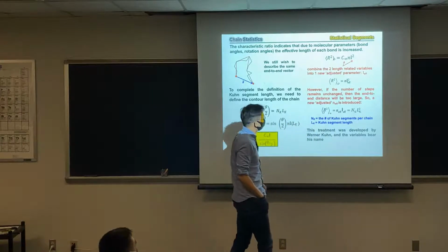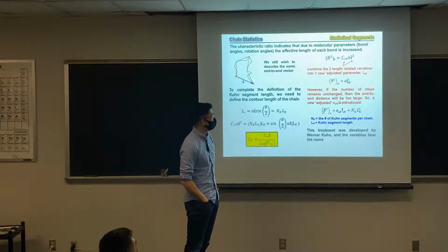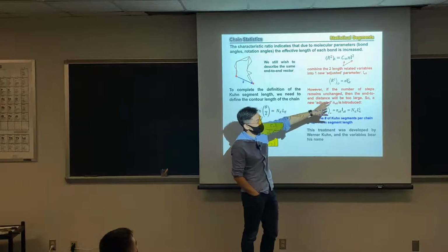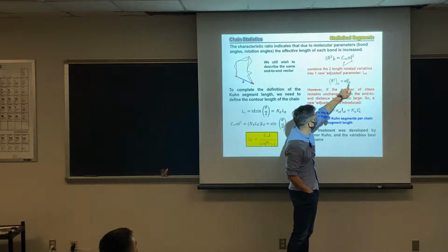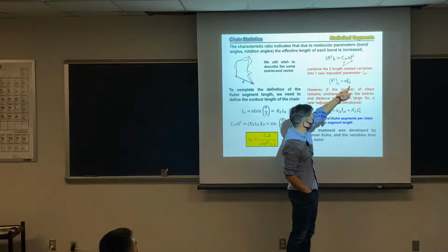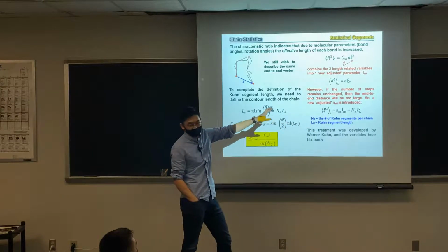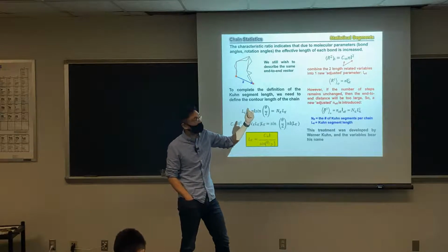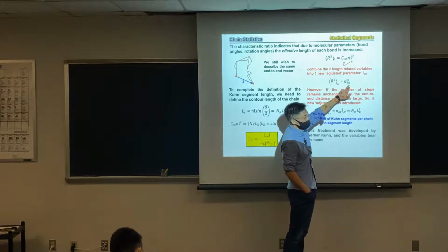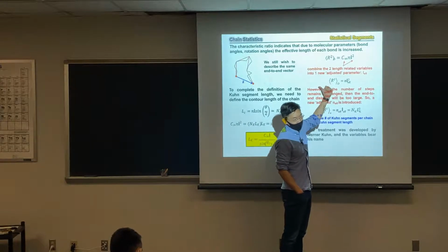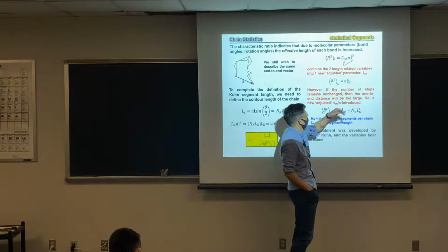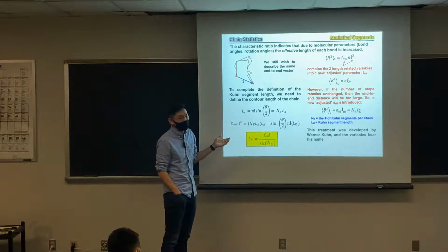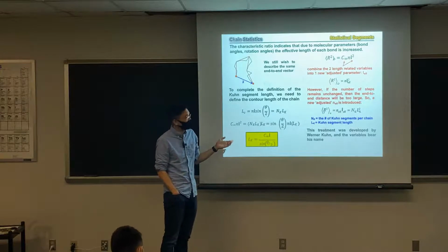So in this case, again, there are two ways you can define that. You can define it with N bonds, with an effective bond length, L effective. That's one way you can describe it. Compared to the other model, which we call equivalent statistical length, now you just fix the N and try to find the effective L to describe it. In the previous case, we defined N, then found a statistical length to define. Either way, they both serve the purpose of replacing a hindered rotation chain with a free joint chain. Okay, no difference.